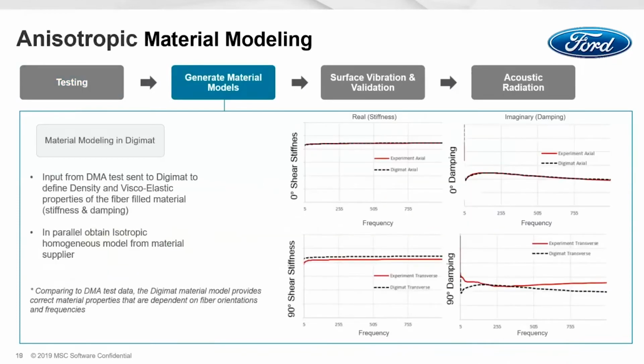Next, we took the input from the DMA test, and those are sent to Digimat. Digimat takes input in 0 degree and 90 degree for stiffness and damping values for this case to create a material model with correct material properties that are a function of the fiber orientation and frequencies. In parallel, comparing the Digimat model to DMA test data, the model provides correct material properties. So here the red shows the experiment and the black shows the Digimat data, as you can see in the